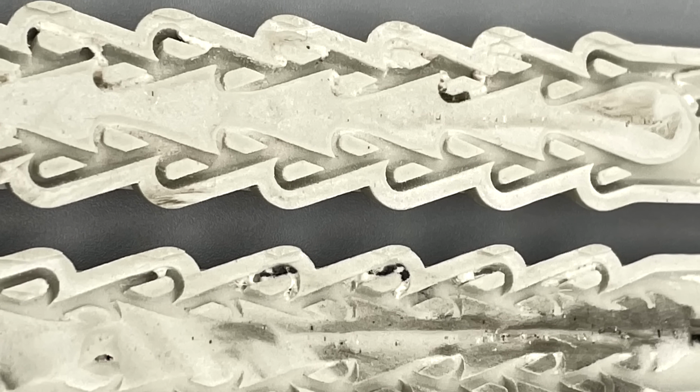After some experiments, I realized that some uncured resin was getting trapped inside the canals of the valve, and during the heating process was stressing the entire part, eventually cracking it. Because I can't access the internal cavities of the valve, I can't really do much. After contacting the manufacturers of the resin, they basically told me that I was right, and also that they would try and 3D print the model and sinter the part.